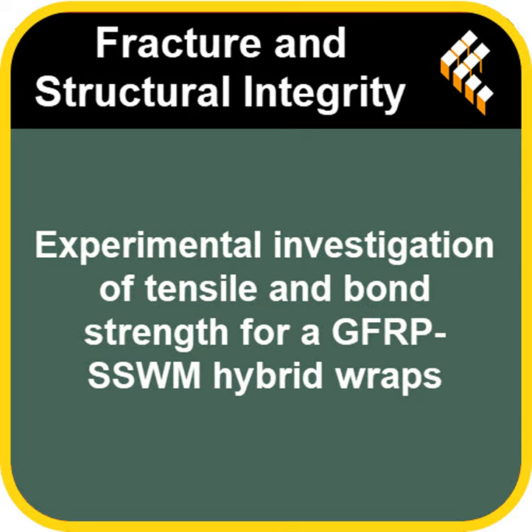But where does it get interesting? The hybrids, I assume. That's where the balance comes in. Configurations like GSG, that's GFRP, steel, GFRP, and GS, they showed really promising performance. How so? Well, take GSG with the Sikadur 30 LP adhesive. It reached nearly 90%, about 89.46% actually, of the load capacity of the pure GGG sample. Wow, nearly the same strength. But using fewer layers of that expensive GFRP, that's the efficiency gain. That's huge for cost.